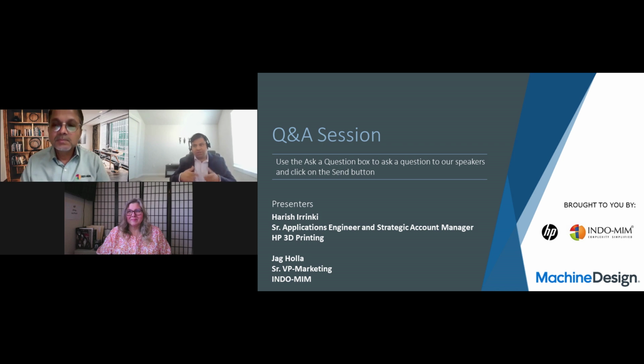As we go on, since HP knows how INDO-MIM sinters and how their powders are, and INDO-MIM knows how our printer works, this becomes faster. Depending on the customer requirements, INDO-MIM and HP are looking forward to developing more and more such materials in the future. It is precisely a two-step process. The first step is to adapt the powder for printability, binder compatibility and things like that. But once you print, the second step is sintering the material to the required density and microstructure. Depending on how difficult the material is to sinter, it may take a little longer. It could be anywhere between 4 weeks and 4 months, depending on how the material behaves during sintering.